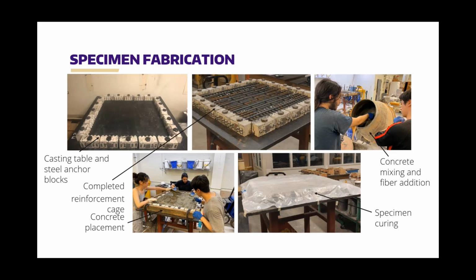To build these panels, you start with a casting table and these steel anchor blocks. You then take all of your reinforcement. All the rebar is actually threaded on its ends, and it's passed through, and then it's attached to the blocks with nuts. And that was something that JP had spent a long time doing. He had to thread a lot of rebar. You can see there the fiber addition. So we have a concrete mixture, which we worked with Cal Portland to get, and now we're adding the fibers and then placing that in the casting table here on the bottom row.